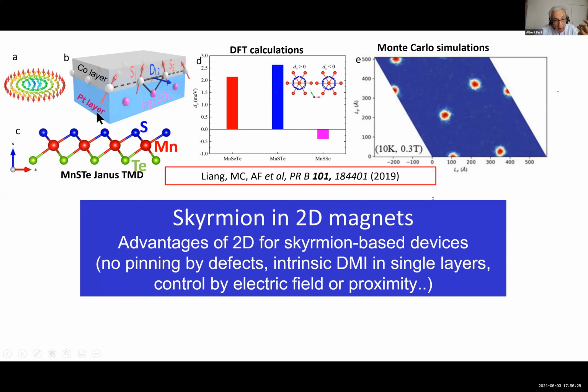And so the calculation performed on this Janus TMD, it's called Janus TMD because it has this asymmetry, the DFT calculation showed that there is DMI in this system, that there is a DMI between the spins of the manganese here. The magnetic element is the manganese, and these manganese atoms are coupled by DMI, the Dzyaloshinskii-Moriya interaction. And you can see that the DMI magnitude can be as large or larger than what is usually obtained with a layer of 3D magnets, cobalt, for example.